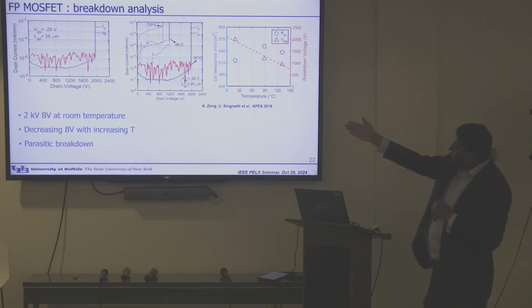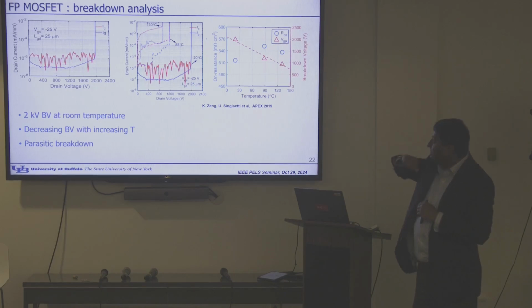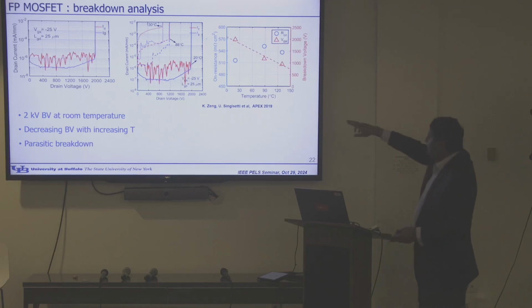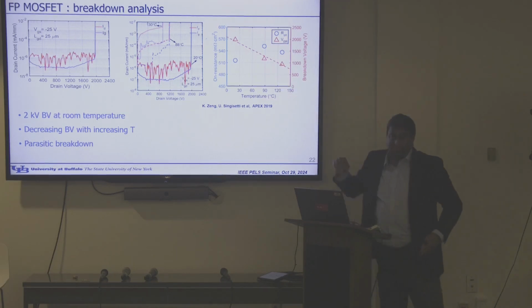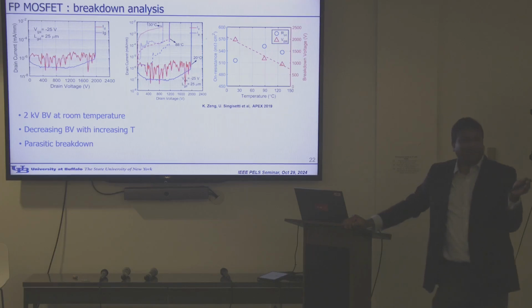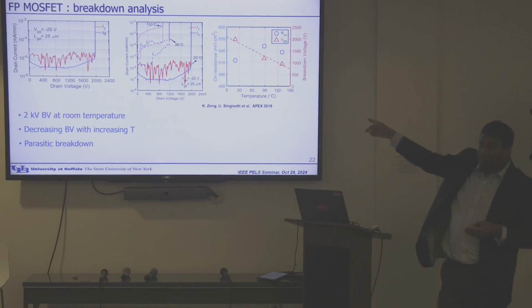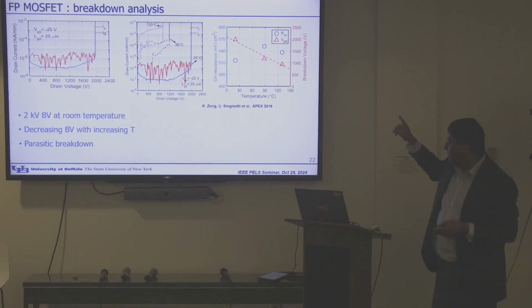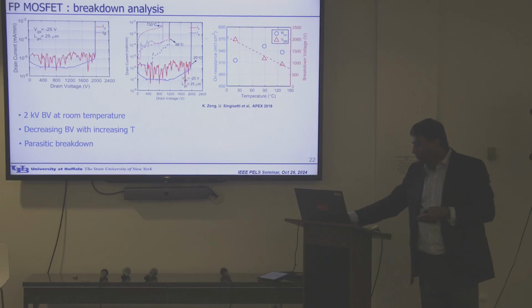So again, it's a different process. We still got the 2 kilovolt, you see in the center on the left. When you go to high temperature, the breakdown decreases. You can see here, breakdown decreasing with temperature, right? Which is a signature that it's breaking outside the device, because if it breaks in the channel, if you go to high temperature, there are more phonons, electrons scatter, they want to ionize, the breakdown should increase, right? And that's what people see in silicon carbide. So here we're seeing decreasing breakdown, which is suggesting it's breaking outside the channel.